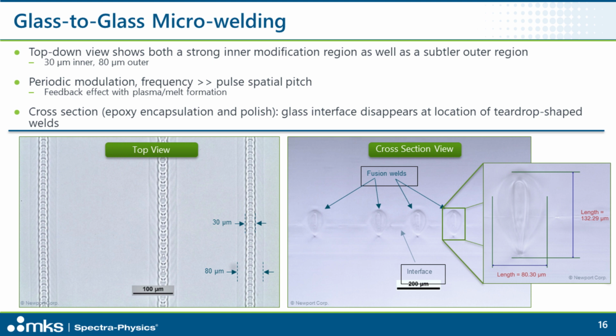Now, you may notice this periodic modulation within the central 30 micron region. This is not due to the individual pulses irradiating the material. The pulse spacing is actually much smaller than that frequency you see there. This may be a feedback mechanism where the melting and the plasma causes a defocusing of the beam, and then as the material translates, it refocuses to that optimal tight focus and creates the same identical modification. So some sort of feedback process is likely at work there.